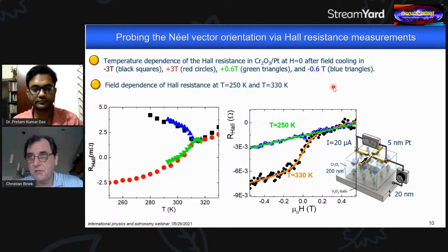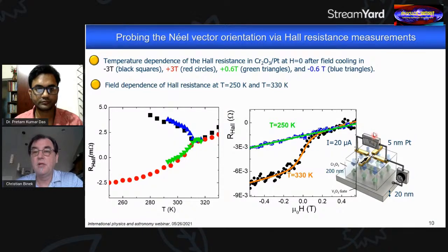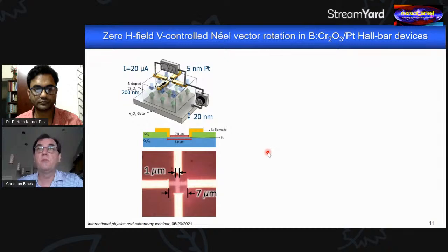That's one possible scenario. Another scenario, and the more likely scenario, if you carefully look into these things, is a spin Hall magnetoresistance effect. And that's most likely the dominating contribution. But the take-home message here is, no matter what the effect is, what you measure is a fingerprint of the orientation of the boundary magnetization. And that brings me now to the devices which we have grown with boron-doped material.